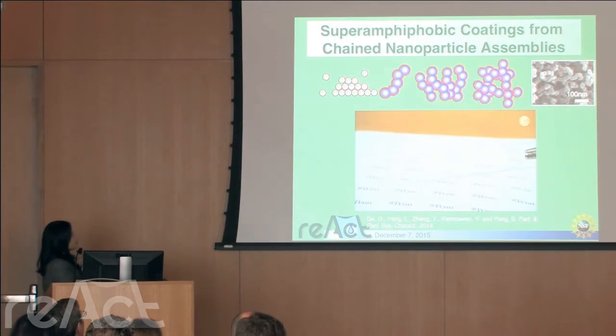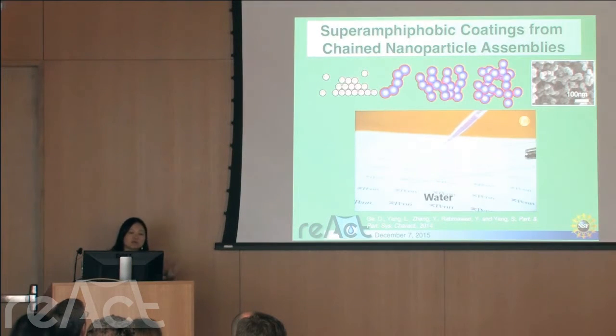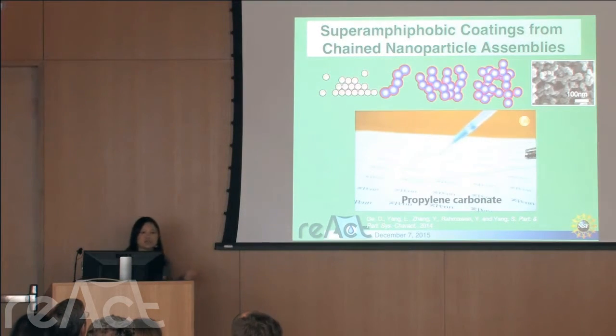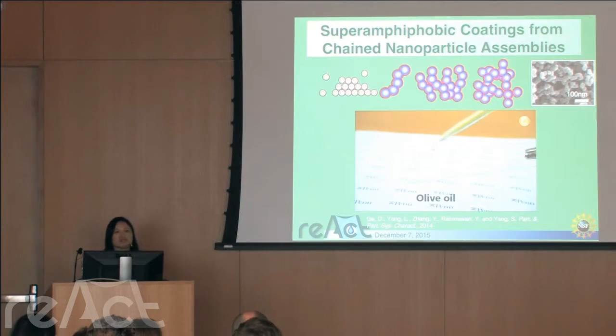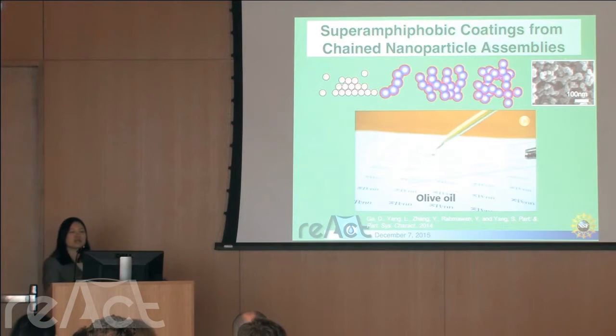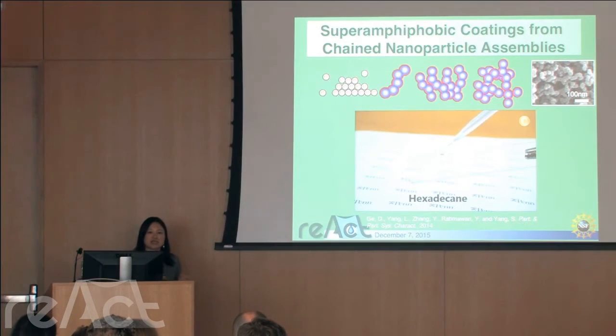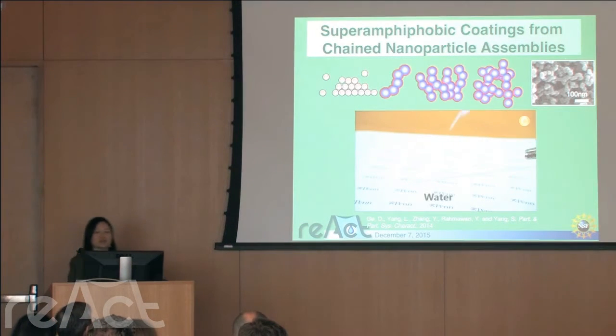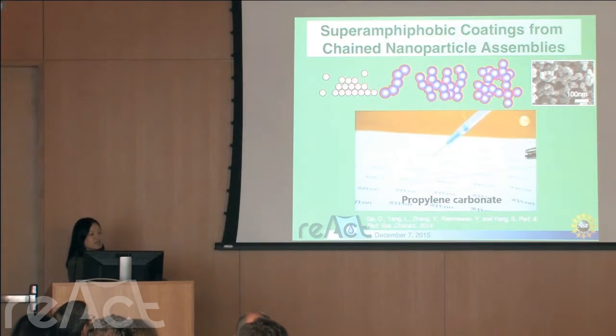One example: oftentimes people talk about spherical nanoparticle assembly. What I want to show you here is another set of nanoparticles. If you chain nanoparticles together, you actually get strings of nanoparticles. They are not nanowires because they're much more flexible. It's like a polymer chain, all right? When we talk about the polymer chain, we always say it's pearls on a string. So if you chain them together, they're flexible. On the other hand, they can aggregate and self-assemble into more porous materials.